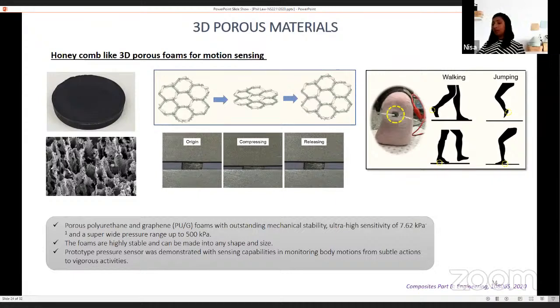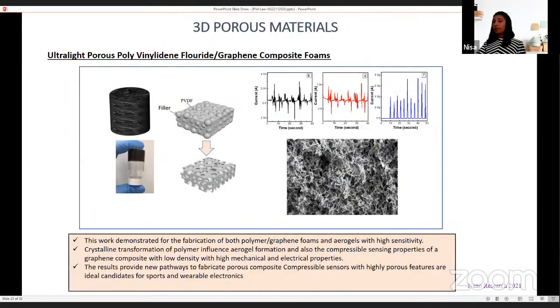These foams exhibited excellent strain sensing properties. We have demonstrated motion sensing capabilities of these materials, like finger bending, walking, and jumping. That shows its potential applications in pressure sensing areas. In another study, we have explored crystalline phases of polymers to make foams. We selected polyvinylidene fluoride and combined that with graphene. PVDF has different crystalline structures. We found that by altering the polymorphism of PVDF, we can exert different modifications on its physical properties like thermal stability and electromechanical properties.